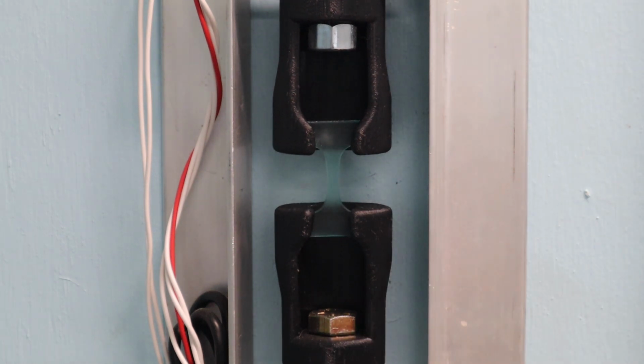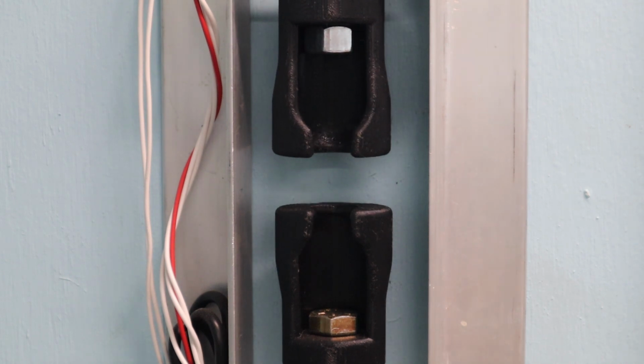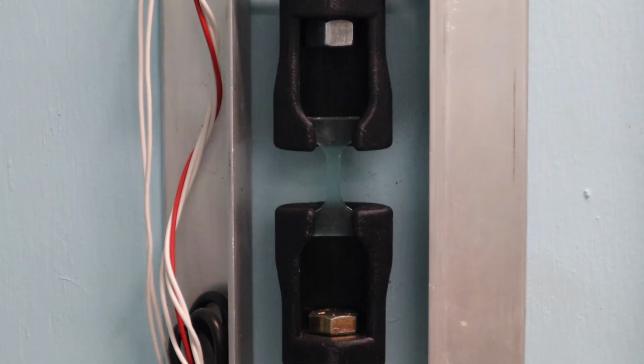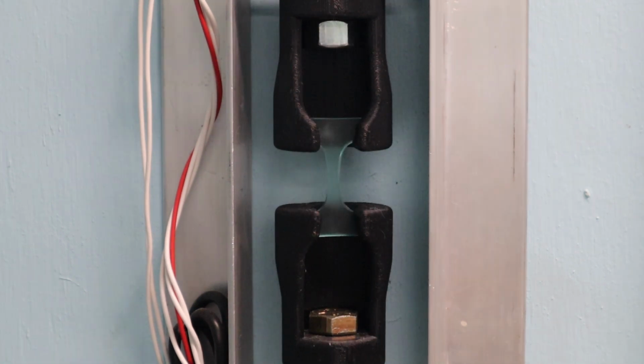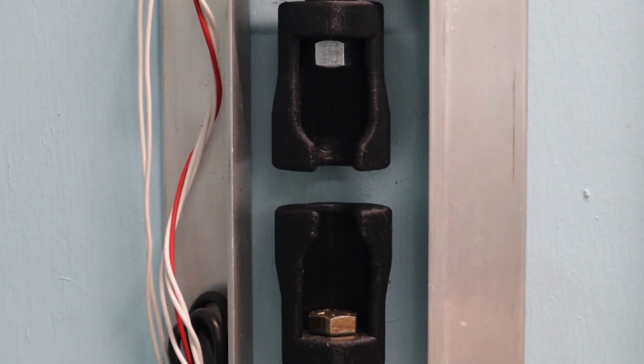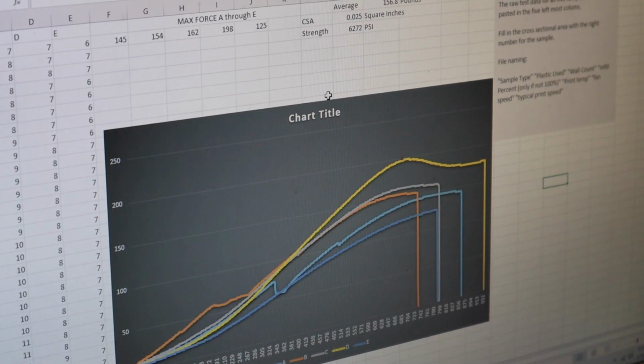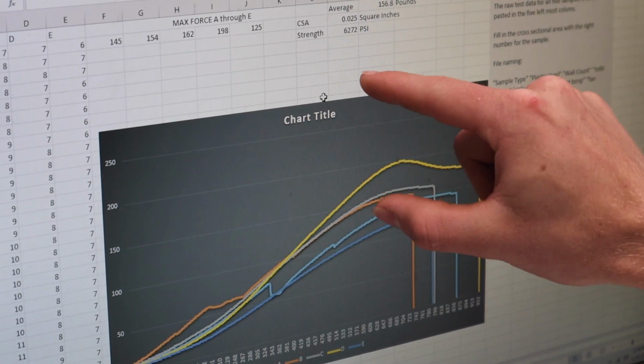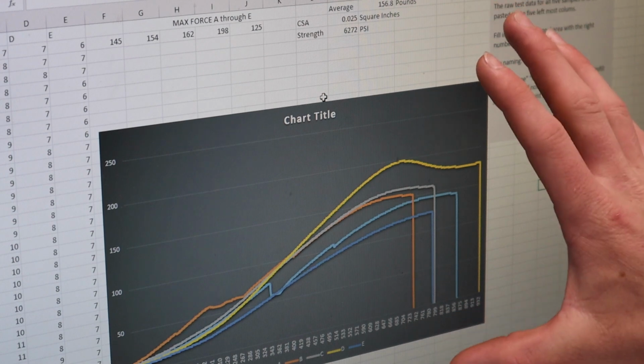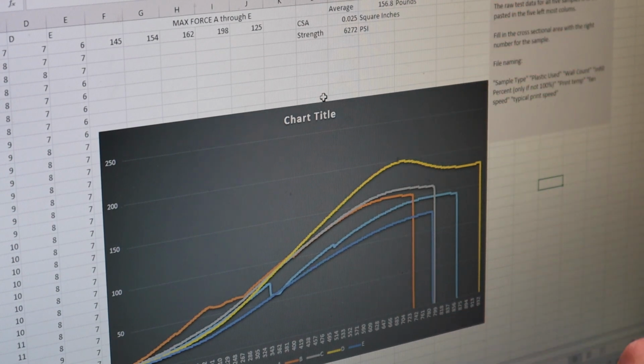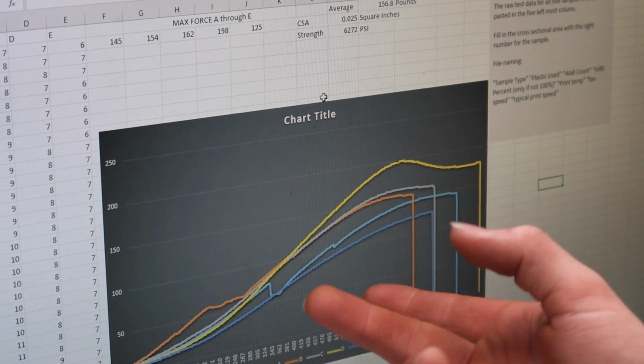These have half the cross section, by the way, of the vertical test sample, so they should break at half the weight. 154 pounds. And 125 pounds. That one was low. Okay, so weird data here. It was significantly less than the vertical test samples, which is really kind of strange because horizontal ones are normally stronger because of the layer orientation.